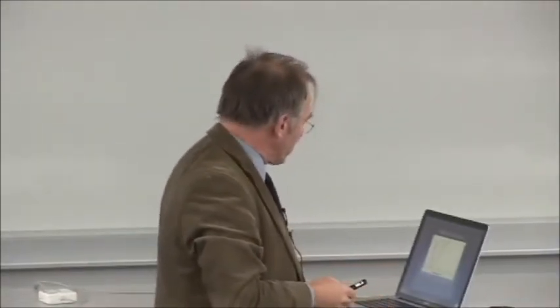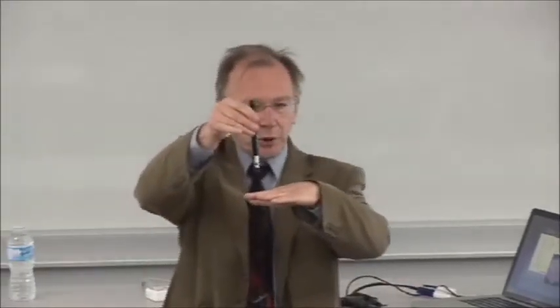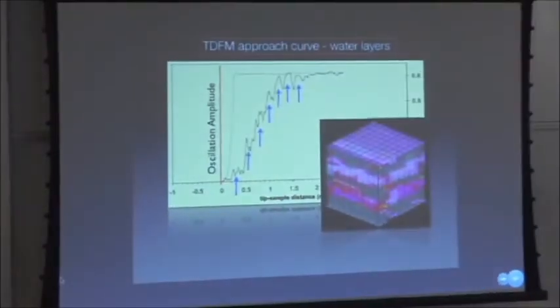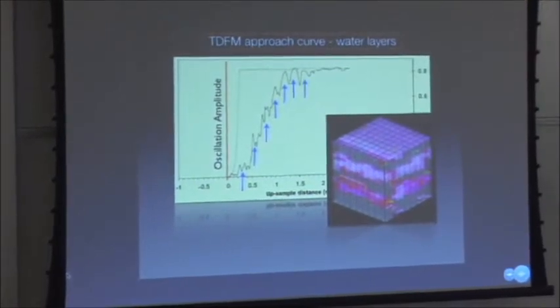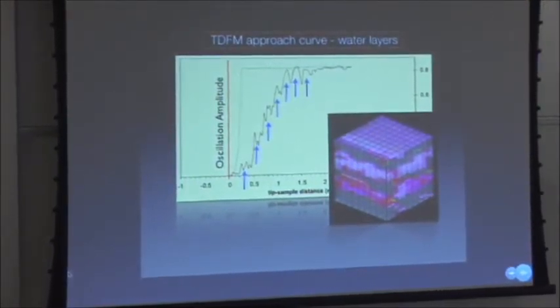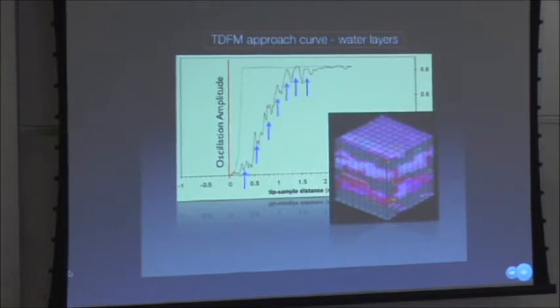What you can also do is do that in 3 dimensions. So now you can do that at every point. You're oscillating the probe and you just move it in and out a nanometer at every pixel. So you can map out the water layers across the surface. This is probably quite important for biology, to know how the water structure is on different regions of a membrane or different parts of a biological structure, where you'd want ordered and disordered water.